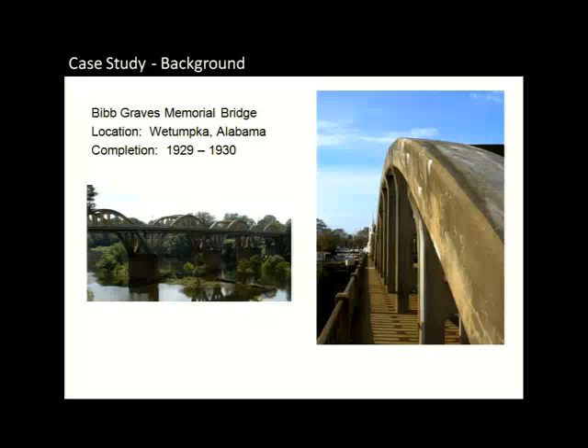We've done a lot of petrographic work where we've taken cores out of the structure. We've sent them off to a petrographer who can actually look at it under a microscope and characterize the aggregates. We've done a lot of work on it in the lab to look at expansion measurements and to look at cement contents. We can't really figure out yet why this is the only arch that has ASR going on, because the concrete and the exposure conditions in all the other arches are virtually identical. But we've been monitoring this bridge for about the past 5 years, and it's still showing a significant upward trend in expansion.